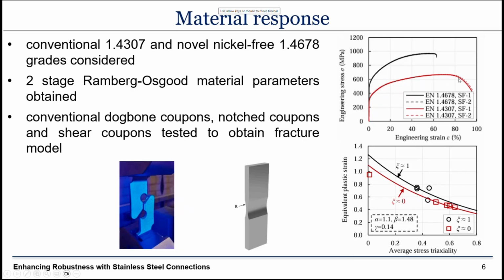We can see that for the conventional stainless steel grade, we have a remarkably high ductility, so the strain at ultimate is about 70%, the strain at fracture even more. The more novel grade has a strain at ultimate of a bit under 50%, but it has a very high strength, so the ultimate tensile stress is just below 1000 megapascals, and the nominal yield strength is about 470 megapascals.